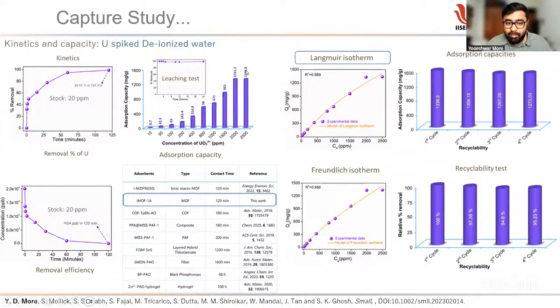We found that in such a case, the adsorption capacity was quite high, up to 1336.8 milligrams per gram. It is very high: 1 gram of MOF adsorbs nearly 1336.8 milligrams. When we did the kinetics, removal efficiency was nearly 100%. In 120 minutes, we were able to remove all the uranium in the given stock solution. The stock solution is 20 parts per million. Our removal efficiency was nearly 99.3% in 2 hours, that is 120 minutes. That is quite fast.